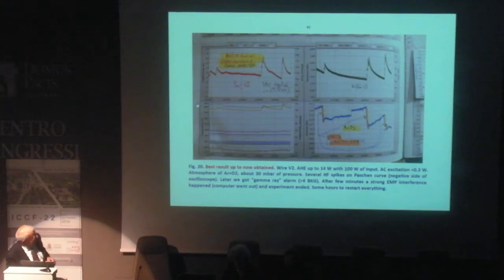And it is the best result, a mixture of argon and deuterium. The argon lowers the voltage for the Paschen regime, so it makes an effect. The pressure is just 30 millibar, and we get about 14 watts, stable.